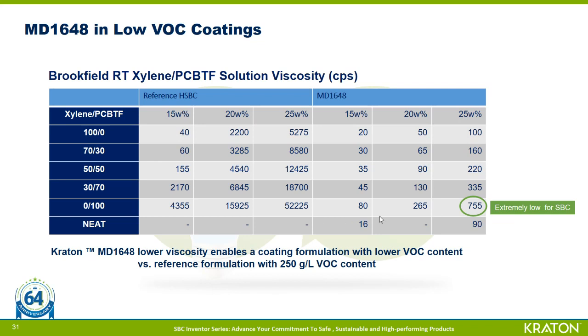And we compare this to a reference HSBC formulation. That reference sample has a viscosity above 50,000 centipoise. So therefore, some of these products, such as MD1648, may enable even lower VOC content reduction due to their significantly low viscosities.